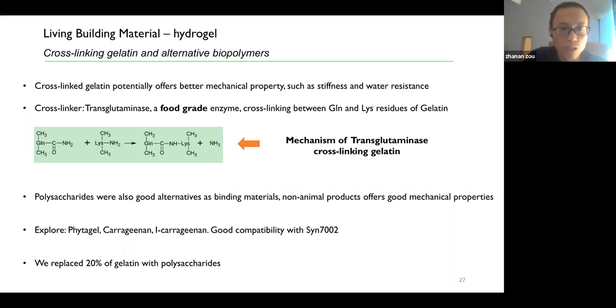Well, for the cross-linking of gelatin, we use a safe, food-grade, enzyme-based cross-linker, which is called transglutaminase. It is completely food-grade, and you can find this in chicken nuggets or something. And the mechanism of this cross-linking is quite straightforward. It just cross-links some residues in the gelatin and produces a little amount of ammonia, which has already been proved to be safe to our cyanobacteria.